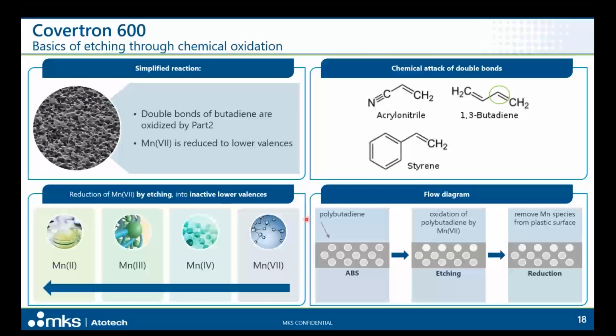Of course, when we discuss the reaction, the basis of the etching is chemical oxidation, and the simplified reaction is that the permanganate, the manganese 7, will be able to etch or attack the double bonds of the butadiene, through this Part 2, which introduces the manganese 7. Of course, in this process the manganese 7 is reduced to a lower valence. Here you can see, in a simplified way, the double bond of the butadiene present in our resin, and as a result the manganese is reduced. That is again shown on the screen: how the manganese 7 moves from the active species to the other that becomes inactive.